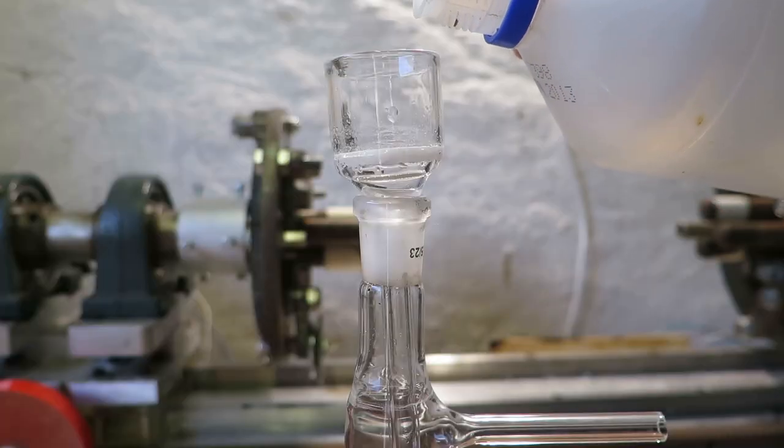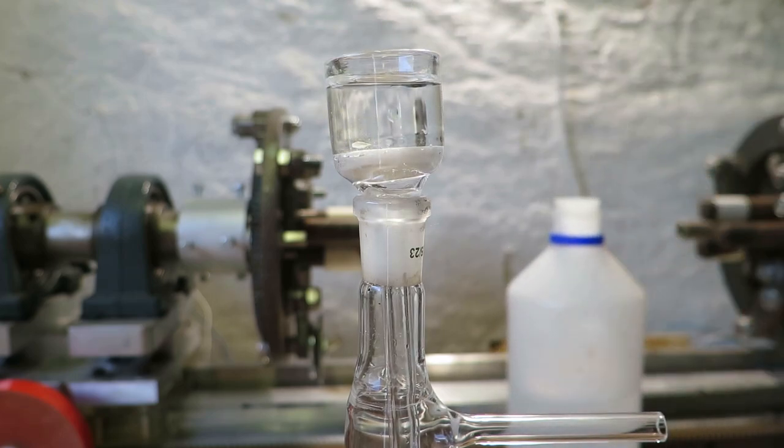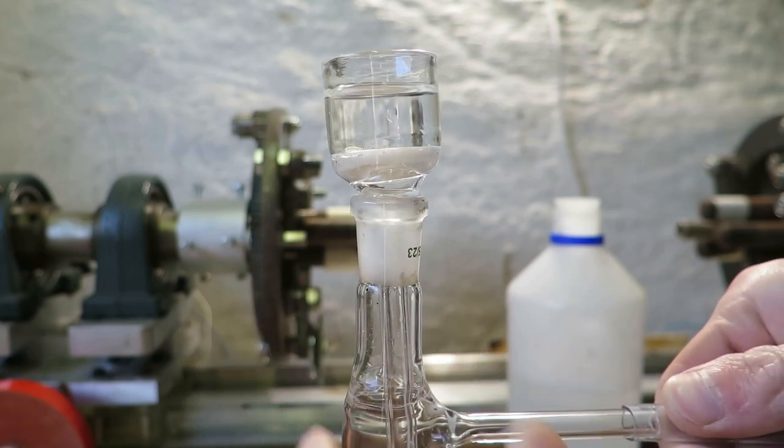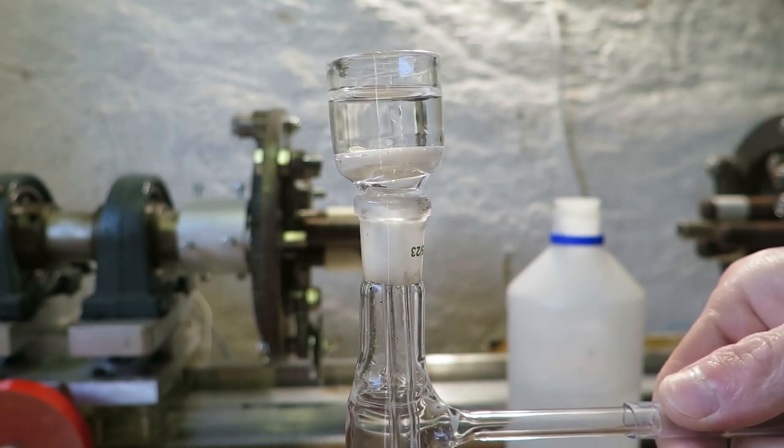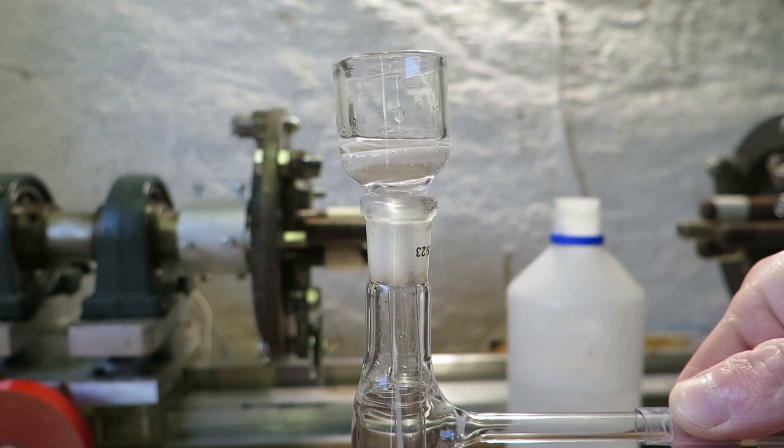In any case, I filled this with water to see how porous it is. It's quite porous, so if you want less porosity you'd probably need more baking time. But overall it does behave as a glass frit filter. So I call this a success.